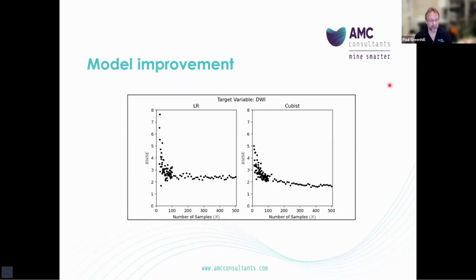So this gives us a mechanism to align both the study level risk that is desired as a target and how far we need to go with respect to the volume of testing that is important with respect to using a predictive geometallurgical model to assess the processing performance. So such a threshold, the threshold at which we don't want to take more samples, is data driven, and it's really not reliant upon rules of thumb or any a priori assumptions.